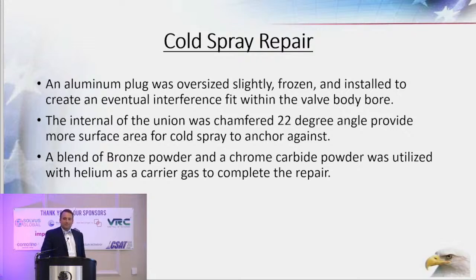Part of our learning experience has been trying to do masking and plugging, trying to prevent cold spray from going where it doesn't need to go, but also being able to give you the features that you need. So we had to come up with some basically bridging. We took an aluminum plug and stuck it down into the bore of the valve body. We froze it just beforehand and gave it a little bit of an interference fit once it thawed out. It gave us a nice tight fit, and then we basically just bridged over the top of it and built up our cold spray, and then we would machine the plug out afterwards. And we've done this a few times with keyways and other components to get the desired profile.